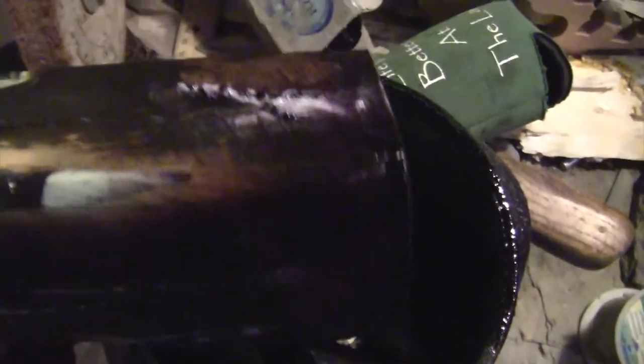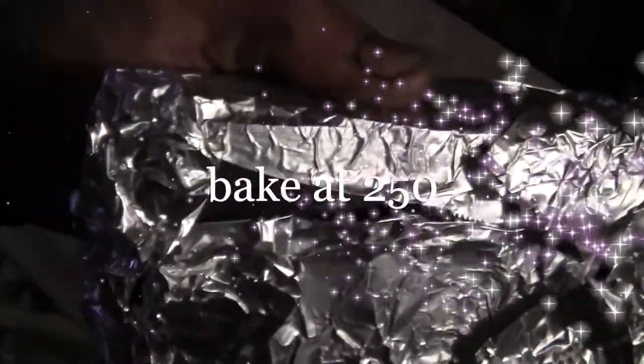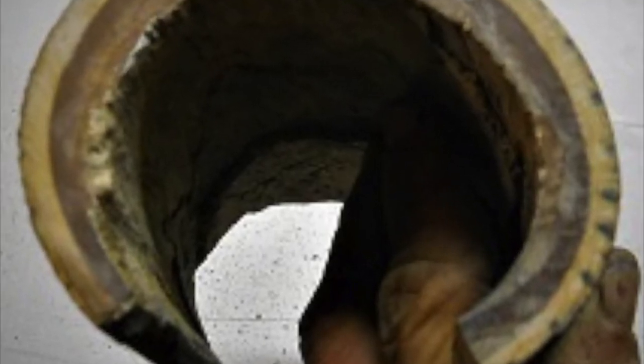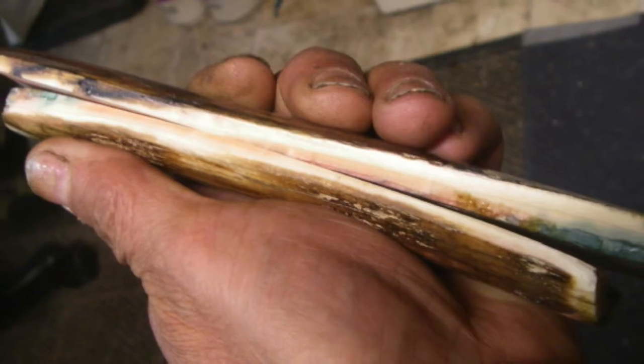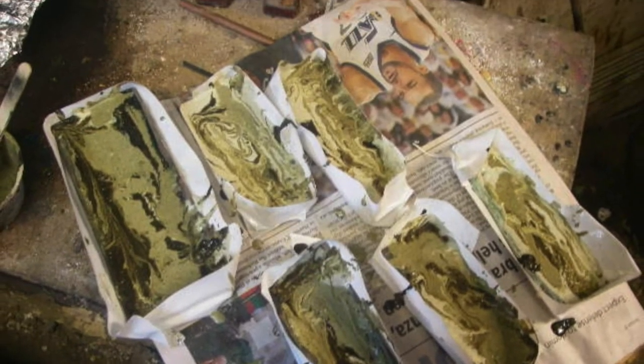I also have a special process where I soak it in more than one dye — I soak it in one end, then another end, and try and make it as cool-looking as I possibly can. The wet, impregnated material has to get wrapped in foil so the liquid doesn't leak out, and it hardens the resin. But even after coming out of the resin, there are other things to deal with, like curves. I can split a curve, but there's still a slight curve, and big pieces can be warped, twisted, hollow. One good way to fix that is to level it all off on the back with resin and then sand it flat.